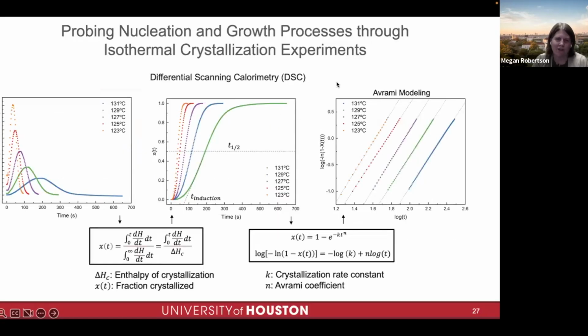We can also study the kinetics of crystallization. Here we're using isothermal crystallization experiments where we heat the sample up into the melt, and then cool down to a temperature below the melting point and hold it for a period of time until it crystallizes. If we do this at a lot of different temperatures like shown here, you can quantify from the raw data the fraction of the sample that's crystallizing as a function of time. From this, we can quantify what's called the half time, the time at which half the sample is crystallized, and also the induction time, which is the time at which the nucleation process starts.